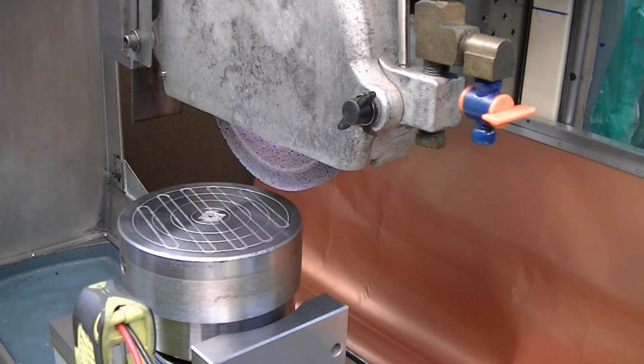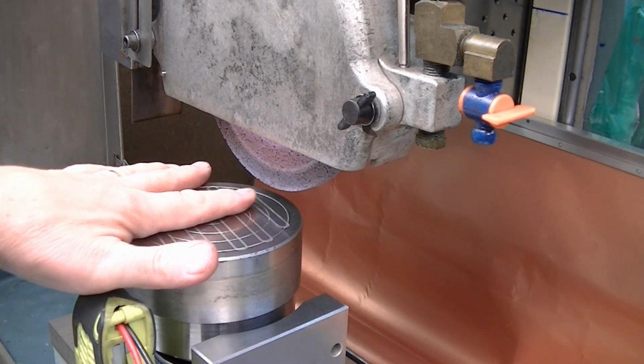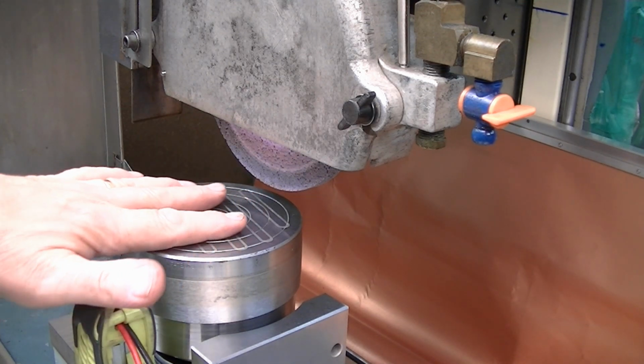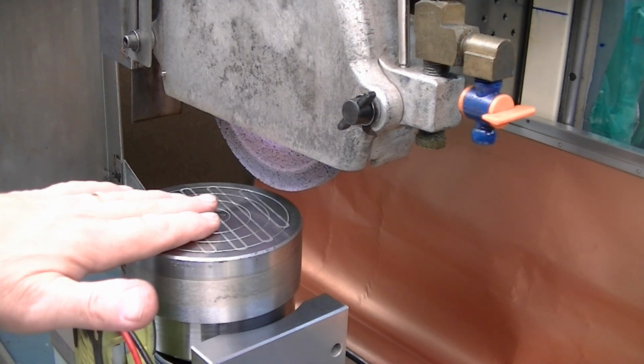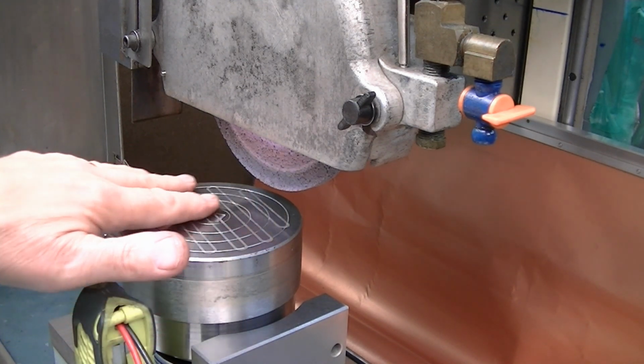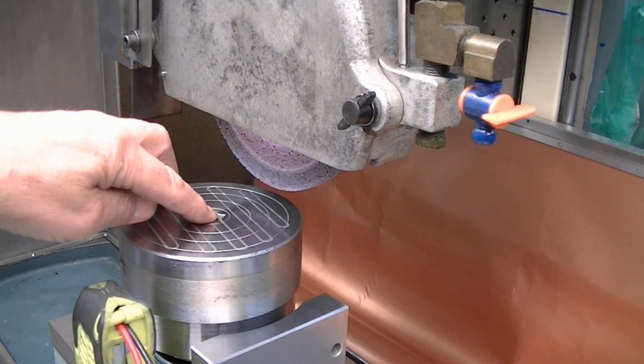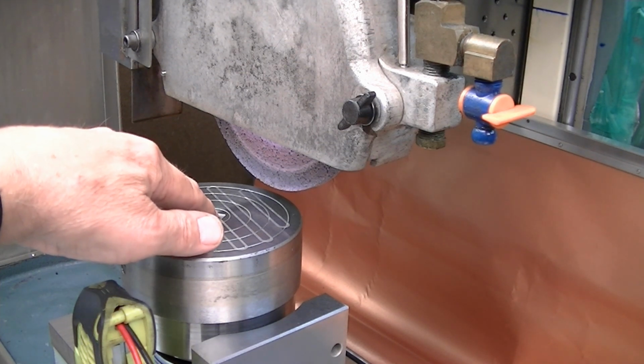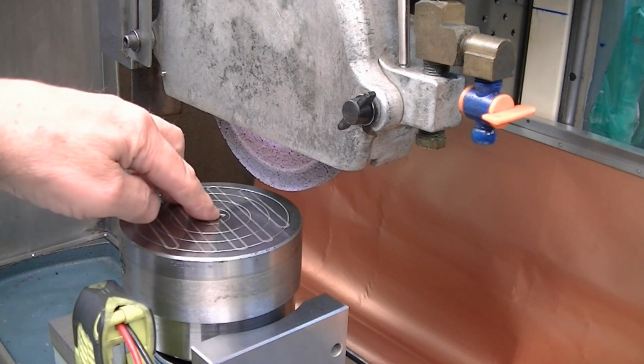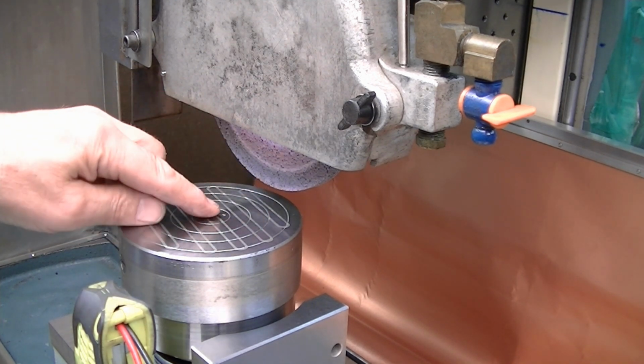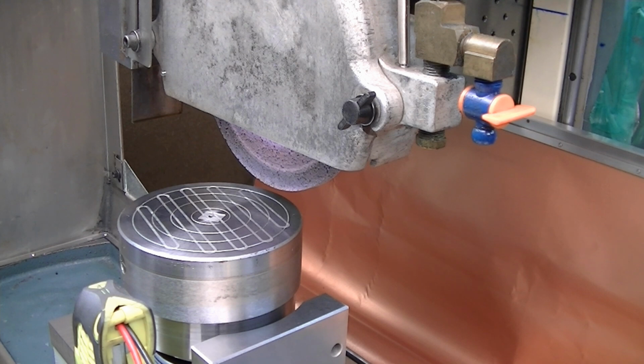As you traverse across, you can end up with a part that has an actual twist in it because the grinder is grinding with a twist. As long as one axis, the z-axis of the grinder here, is reasonably straight, you're going to be able to get a part that is very flat. Now, flat meaning parallel in a sense, but if you adjust all the conicalness out of the part, if you want to call it that, and get it to where it measures the same thickness out here and in the center, then you've got parts that are extremely flat. So it basically enhances the ability of a grinder to produce very parallel cylindrical parts better than you can do in the chuck.